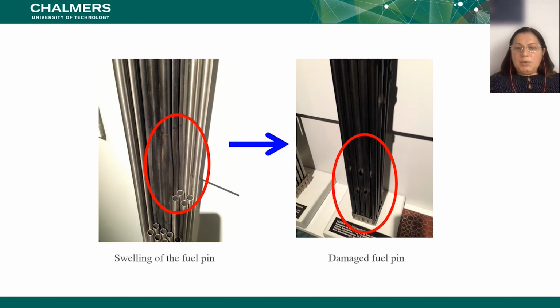And when you have this type of swelling, you see, I'm not sure these are the best pictures you could see, but I took them myself, and I apologize for my skills, but you can see that the swelling can look like that. So what happens is basically that it's not only swelling, but it's disturbing the neighbors. That means that you will have all the conditions to damage other cladding tubes around it, and that means that from your nice stack of tubes here, you actually can get quite a lot of damage. And here you see that due to the pressure, it already exploded.